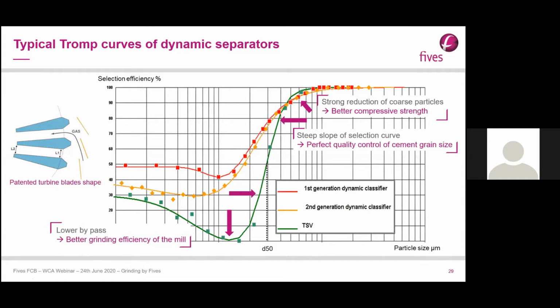Here is what you probably know. It's the Tromp curve with the different shapes of Tromp curves achieved with dynamic separators, starting from first generation separator with here high bypass, nearly 50%, and very smooth slope of the selection curve. If we look at the green one, the bypass comes down to 0%. Of course, not in all the conditions, but in conditions with low specific load and not too fine fineness, 0 is an achievable value.